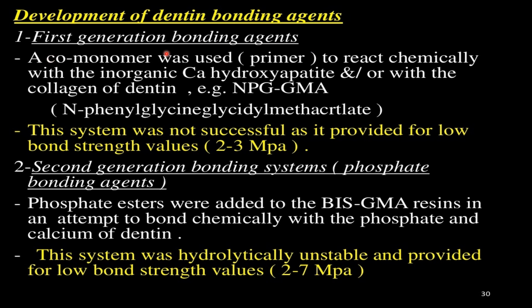Development of dentin bonding agents: first-generation bonding agents used a comonomer, a primer, to react chemically with the inorganic Ca-hydroxyapatite and/or with the collagen of dentin, e.g. NPGGMA, N-phenylglycinoglycidyl methacrylate. This system was not successful as it provided for low bond strength values, 2 to 3 MPa.